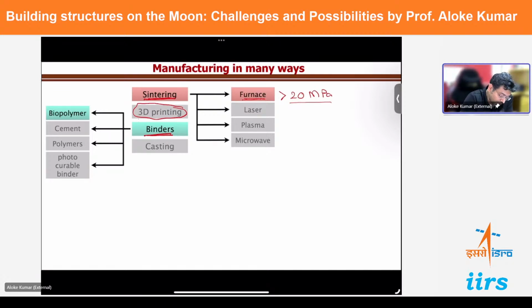We have also done 3D printing, which still gives slightly weaker bricks, but it's good enough. We have used different types of binders. So we realized, when we used guar gum, that you don't have to use just bacteria. You can also use biological polymers, and that's giving very good results. So we've recently used biopolymers to construct bricks, and we have gone one more step further. Till now, all the bricks were being constructed in an earth-like environment in the lab, right? I mean, I cannot construct a moon-like environment in my lab.